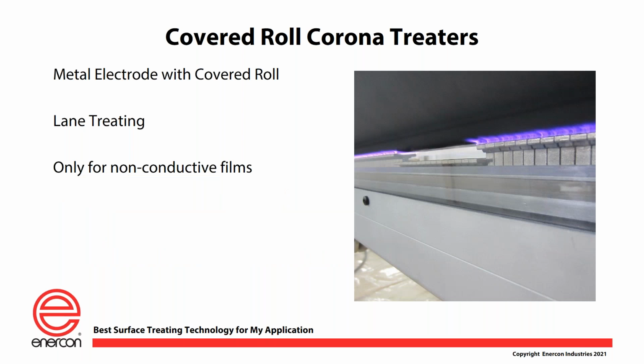So covered roll treaters look just like the picture shows here. This is a very common design that is used in film extrusion, mostly blown film, but sometimes cast film as well. And you can see the segments there where we can actually apply treatment just where we want it. Recently, I had the benefit of working with a client who has a 55 or 60-inch wide web, but they really only want to treat 12 inches. Now that 12 inches can move around. It's not always in the same location. So an electrode assembly similar to what's pictured here is great for that, because they can move that area of treatment to wherever they need along the entire 50 or 60-inch web width.